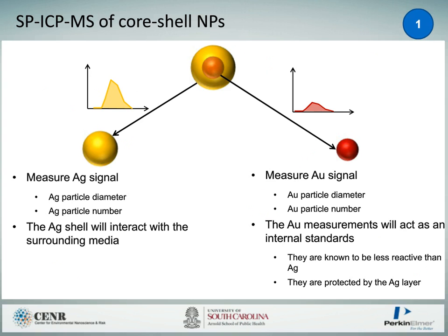So I'd like to talk about single particle ICP-MS and core shell nanoparticles. In this study, the way we use them is by taking the gold signal and then taking the silver signal, so we'd get them separately. And when we measured the silver signal, we'll get a particle diameter and a particle number for the silver, and this silver will be allowed to react with the surrounding media. When we measure the gold signal, we'll get another particle diameter, which will be the gold core size, and we'll also get a gold particle number.